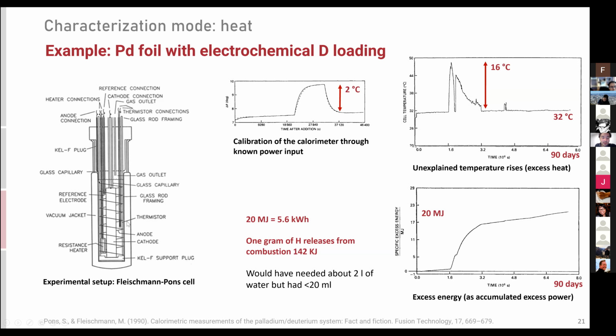by applying a voltage. There were temperature sensors around, calibrated such that a certain temperature could be mapped to a certain power input or energy input in equilibrium, and the other way around. So here you have over time the temperature response of the cell. The applied potential and current was constant, and the applied input power, and then the output power that this temperature change corresponds to, fluctuated, and had this large excursion, a 16 degrees centigrade increase.